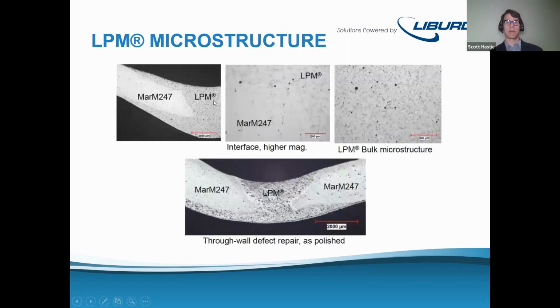So this is just a picture of through wall damage on a leading edge of a vane. Here you can see the LPM material and the base alloy, and it's got a typical braze structure, but generally you're going to see less porosity than on a typical braze repair, and that owes to the two-part process that we use. And here you can see after machining, we've got the wall thickness built up to the original size, and this is ready to go back into service.